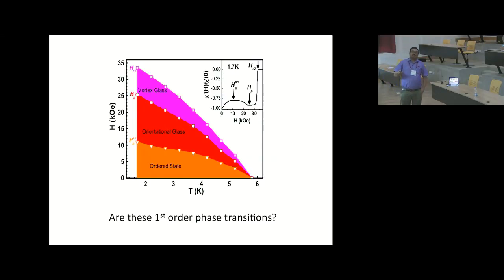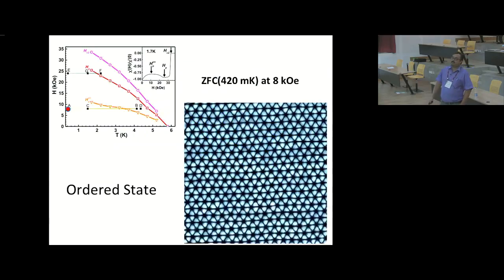They are much more difficult here because the background specific heat is extremely large. So measuring the latent heat over that is a very small change, and that might not be easily detected. So we tried to see if there is indeed hysteresis, if we can identify superheated and supercooled states across both these transitions. So for this, first we look at this lower transition, ordered state to orientational glass.